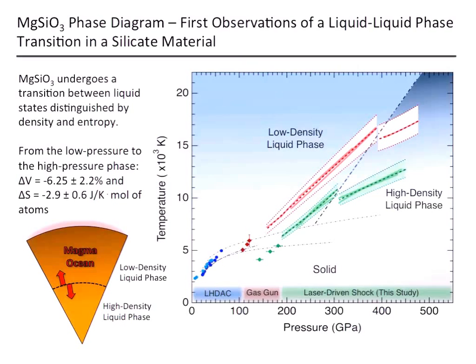I did experiments on two different polymorphs: a single crystal, shown here in this greenish color as the single crystal Hugoniot, as well as a glass, an amorphous starting material. So it's the same composition, but different initial densities. And if you got a glance at those Hugoniot equations, you saw that rho naught, the initial density, was in there. That determines the end state you achieve.